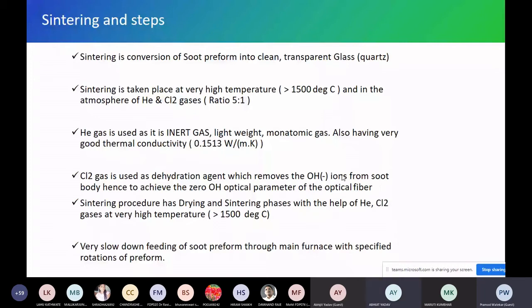During sintering, we generally send helium and chlorine. Helium is useful to reduce bubbles. Chlorine is very useful to reduce oxygen and OH related losses. If you want to take out OH ions, water is everywhere, right? So we want to take out that OH, we must send Cl, and HCl is a gas, so it goes out. And our glass is free of water molecules, and that's why we have our fiber nowadays. Recent latest fibers have very low, nearly zero loss, near the scattering level of attenuation at 1383 nanometer. That is the OH water attenuation. It is negligible attenuation at water level nowadays.